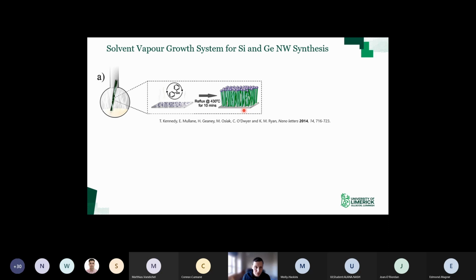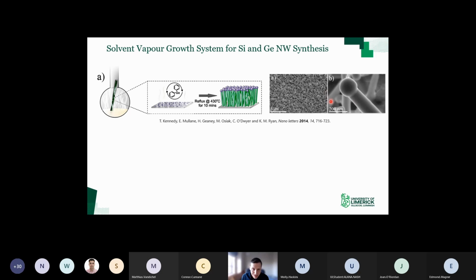So we decided to look at germanium first, I suppose, because germanium not only has a high capacity, it's not as high as silicon, I will say, it's about a third that of silicon, but it has much higher conductivity and a higher lithium diffusivity. So we decided to look at germanium first. This is the SEM of the nanowires after growth, so this is pristine material. And you can see you do get dense nanowire growth across the substrate. And there's a high mag image there where you can clearly see the tin seed at the end.